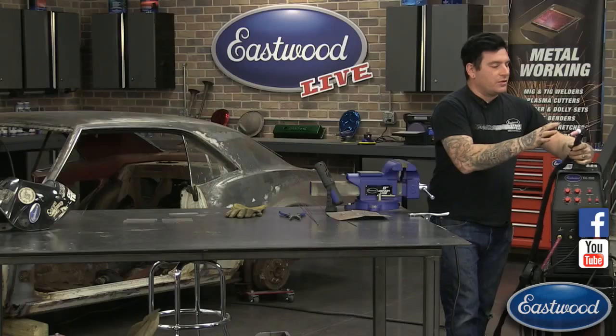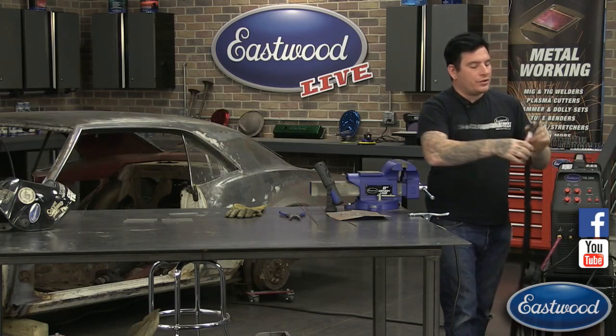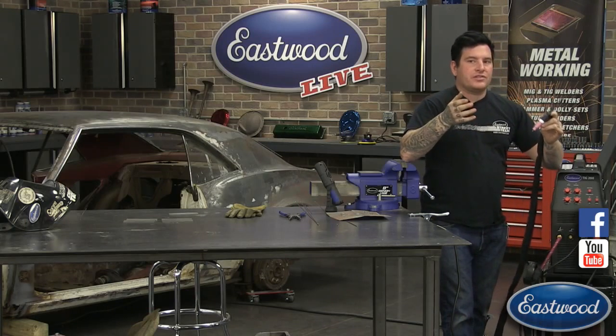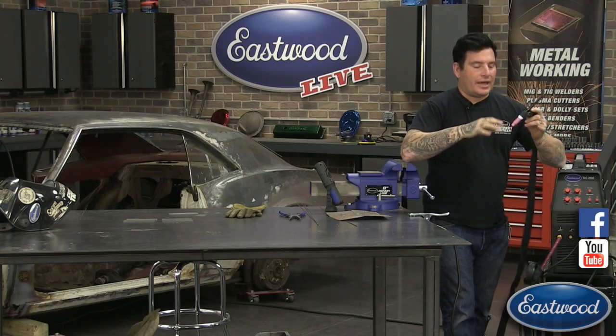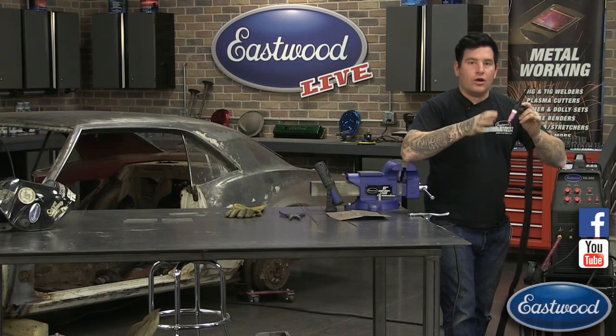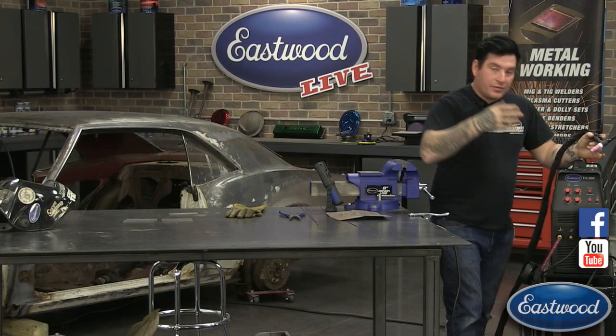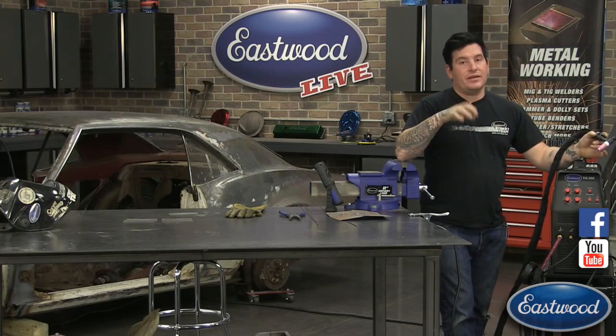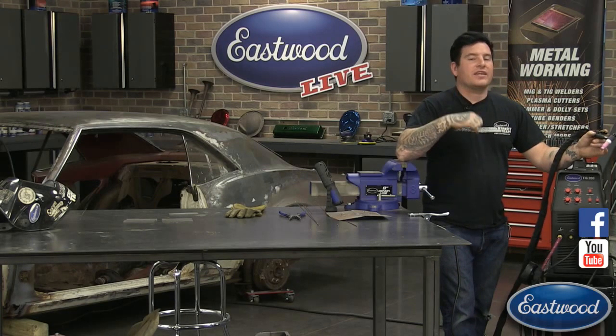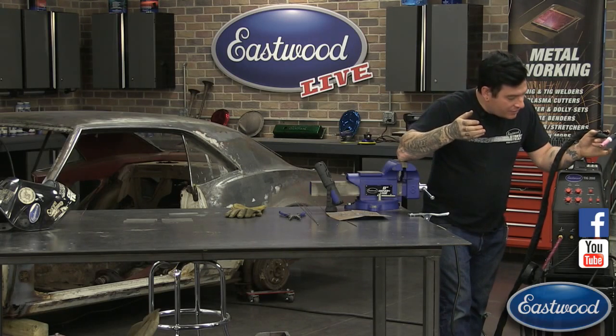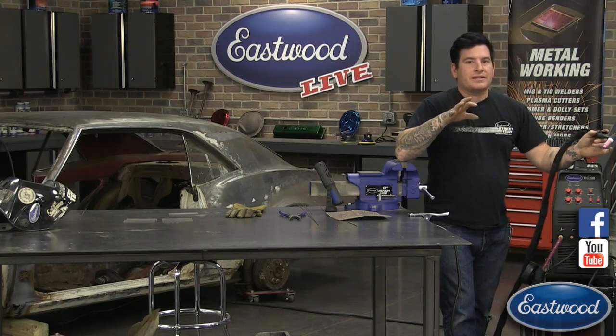Post flow, that is after we weld. After we're done welding, we're holding the torch over our workpiece. You leave a little bit of gas flowing out of the actual torch over the area that you welded, and that's going to keep the weld from getting any contaminants in it. This is especially important on stainless and aluminum. It's really important to get that extra bit of gas at the end that's going to keep the weld from getting a contaminant in it.